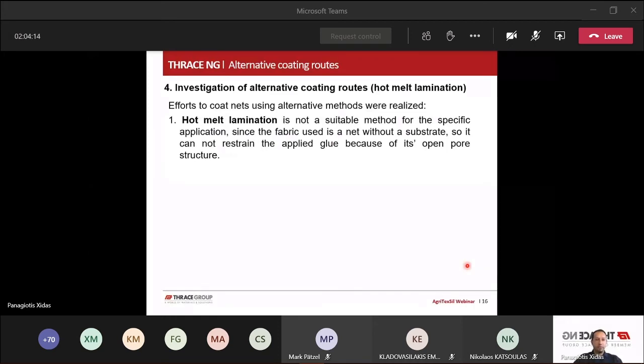Task number four was the investigation of alternative coating routes like the hot melt lamination, because here we have lamination machines, and we tried to take advantage of the hot melt lamination, but this was not suitable for this specific application because we are using a net, and a net has no substrate. Also, it has an open pore structure, so the glue was passing through the net and causing problems to the production process.